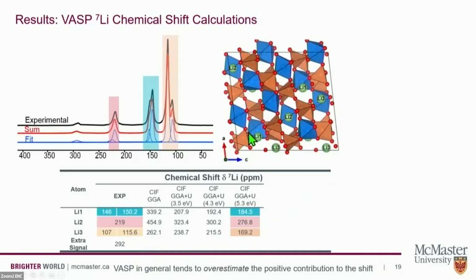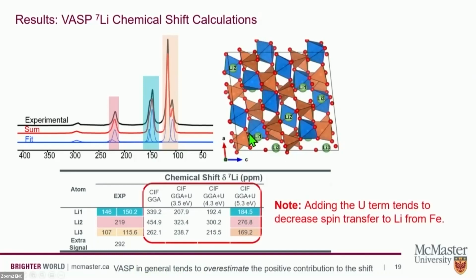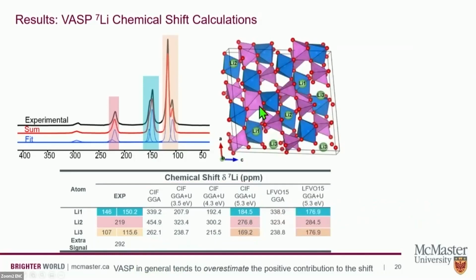So this is for the original structure. We then did the same thing with the new structure, fully occupying the secondary set of vanadium sites. And we see that that doesn't substantially change these chemical shifts. If we keep in mind that this difference between the experimental and the calculated is what we're going for, these are still within that realm for each of these new chemical shifts.